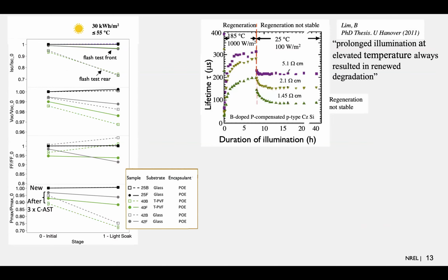So we looked at the literature, and the only literature that I could find that showed this kind of behavior is out of ISFH in Germany, where they did the stabilization procedure at high temperature and illumination, and then, more or less like us, they put it out under regular ambient temperatures and modest light, and then they saw a degradation. And the issue was that it was a boron-doped p-type, but phosphorus-compensated CZ silicon.